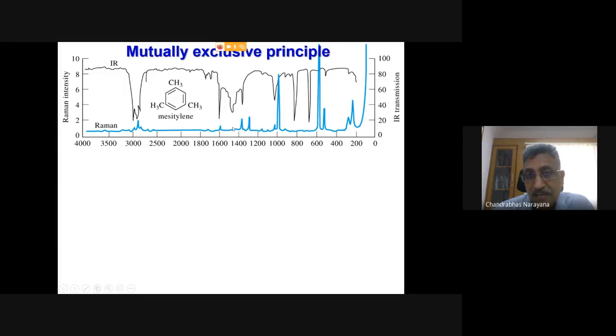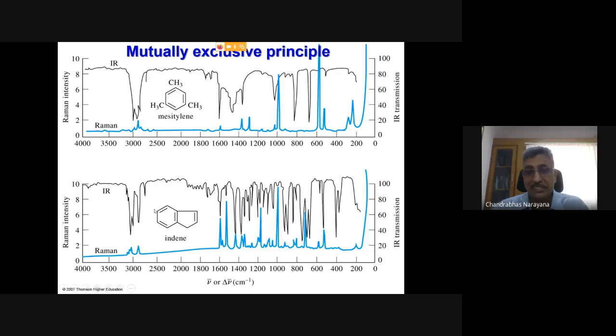This frequency is not having any matching. This frequency is not matching with this. It is slightly shifted. There are frequencies here which are not matching here. So you can see there are frequencies which do not match. Whenever the molecule is symmetric, the benzene rings are symmetric, then the Raman active modes are not IR active, and the IR active modes are not Raman active. But the moment you remove the symmetry, you see that modes can be both Raman active and IR active. So basically, this is one of the problems: if your center of inversion is there, then the mutual exclusion principle is followed.